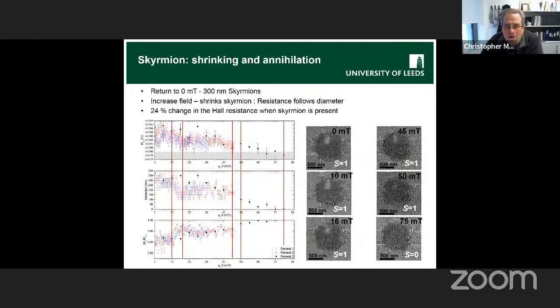So we got our Skyrmion in the disk, and again, we applied a field to squeeze it down. As we go to 10, 16, 45, 50, it's shrinking. At 75, it's gone. We've got a uniform disk, and we can track the Hall signal, which goes down as we squeeze it down. These red lines correspond to the fields with the images. We can measure the diameter, and we can measure the magnetization in the disk, based on the image. And these are various sweeps up and down before we annihilate the thing. So it's somewhat reproducible.